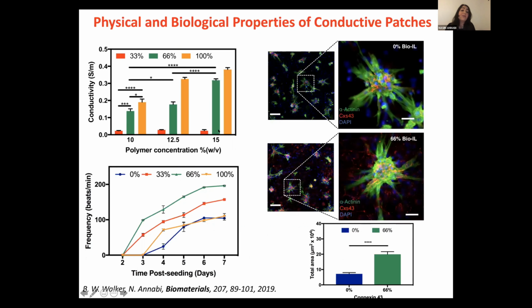For example, here you see that for different scaffolds formed with different polymer concentration, as we add different amounts of bioionic liquid on this scaffold, we can tune the conductivity. So with 100, we get highly conductive scaffold. By adding 66, it's average, and when we add 33% bio-IL, the conductivity is lower. So basically, we can make substrate with a wide range of electroconductive properties.